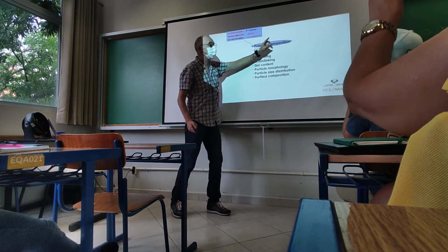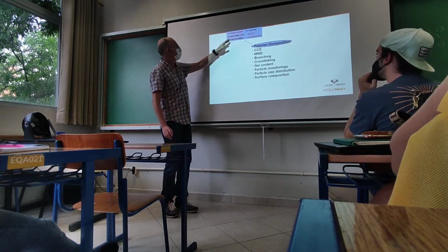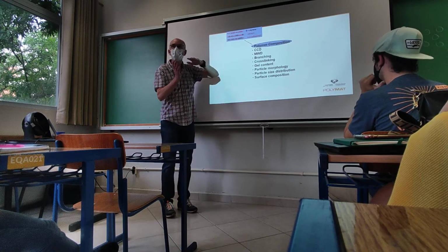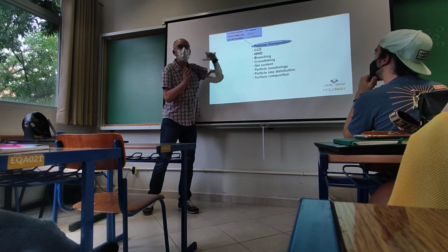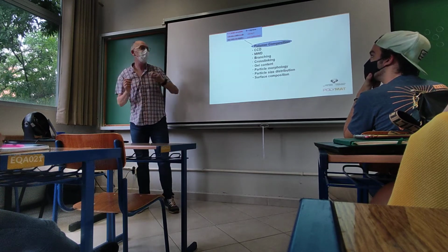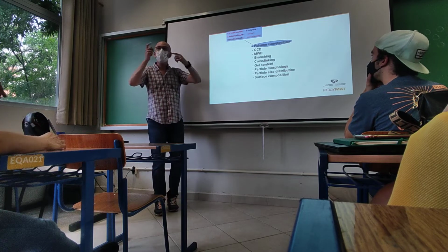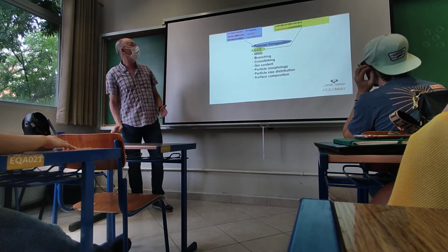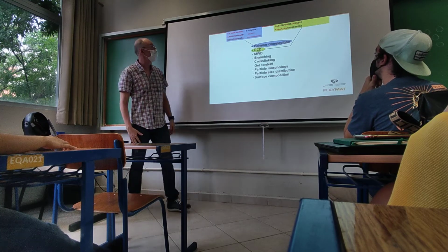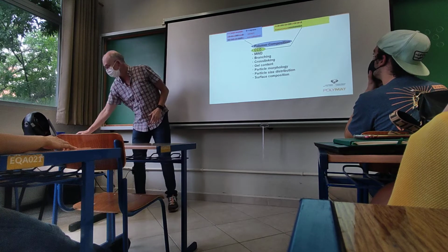Imagine that you are polymerizing two monomers, like butyl acrylate and styrene. Depending on the composition, you might have a polymer which is tacky, so sticky, or you might have something which is non-adhesive, which is brittle. It has plenty of styrene. So, by combining one and the other monomer, you can produce copolymers of the right properties. Or the chemical composition distribution, how the monomers are distributed in the chains.